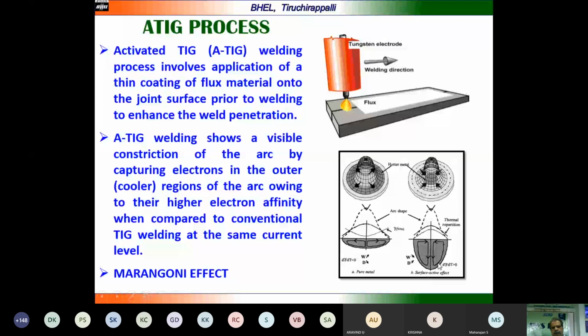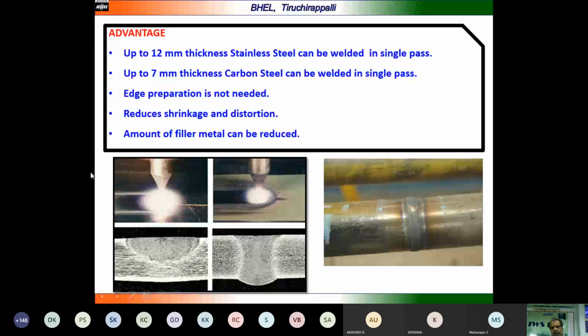That is what we have experimented, and I was even involved in the project to develop this for up to 7 mm wall thick tubes of carbon steels and alloy steels. 7 mm we welded successfully in a single pass with square butt edge preparation. There is no need for any other edge preparation, only square butt edge preparation. No root gap is required, and it reduces the shrinkage and distortion allowances.